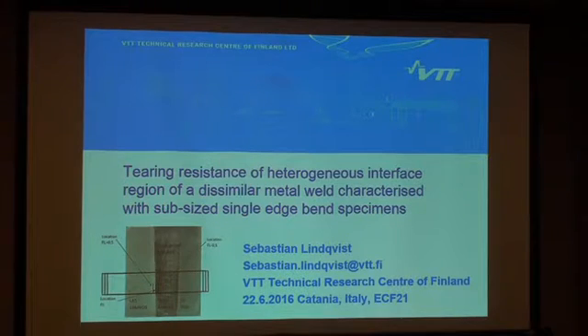A problem with the current situation is that all the standards and systematic procedures for characterizing these specimens, or dissimilar metal welds, are developed for homogeneous materials. And there's no standard for heterogeneous materials. So we need more information on the material behavior in these dissimilar metal welds, and based on experimental investigations, we also try to develop a standard for these materials.